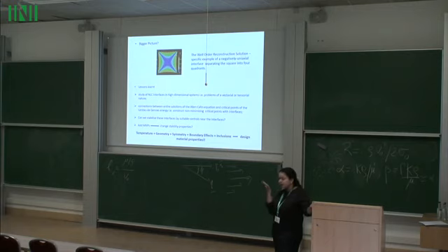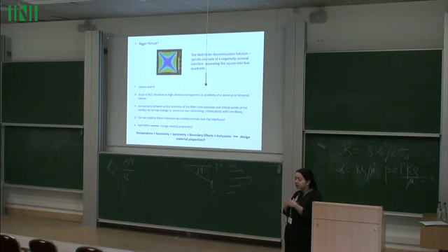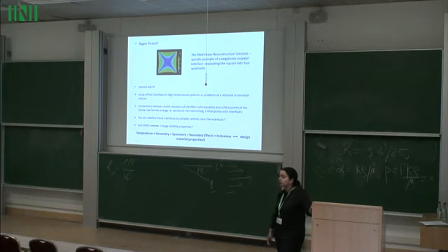But also, I think you need 5 degrees of freedom to describe the state anyway. So you have 3 degrees of freedom associated with the eigenframe, and 2 degrees of freedom associated with the actual degree of orientational order. So you need 5 degrees of freedom in the object itself to describe the orientational order. So in the problem with the square, you use the 3 by 3 Q tensor and reduce it from 5 degrees of freedom to 3 degrees of freedom, right?